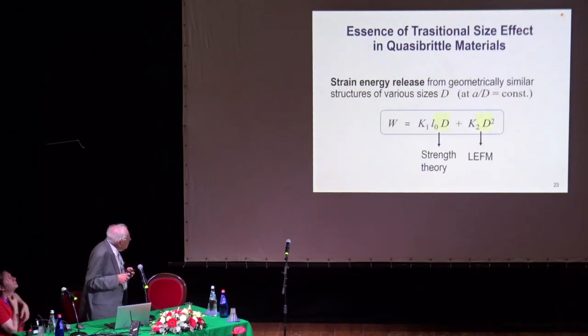So to summarize, the main effect is that in quasibrittle materials, but also now in the case of yielding plastic hardening materials like aluminum, the energy dissipated is some constant times the material characteristic length size linearly. This is a constant too. Another constant times size squared. And this is characteristic of all these problems in general, and they inevitably use that same formula and no other formula.